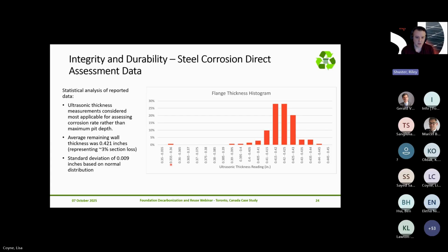In our experience, these ultrasonic thickness measurements are most applicable to assess the general corrosion rate for driven piles, as opposed to pitting corrosion rate. And so we'll get into that in a second on the next slide. But here we've shown the data with a normal distribution and a standard deviation of about 9 thousandths of an inch.